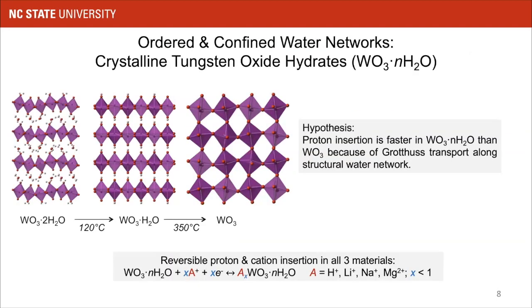It started off with our interest in understanding the role of ordered and confined water networks in crystalline tungsten oxide hydrates. So we saw in Deborah's presentation how hydrous ruthenium oxide behaves as this ideal capacitive material with very high specific capacitance, this continuous network of water molecules and conductive metal oxide particles. And so there's always an interest to find other materials, perhaps lower cost, that would exhibit similar phenomena. So we took this approach of looking at a material that contains structural water molecules, but now it's a crystalline material.